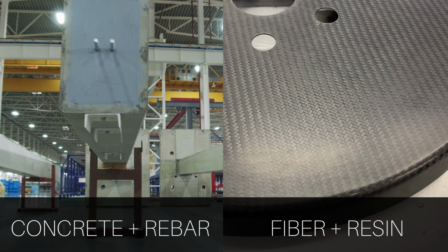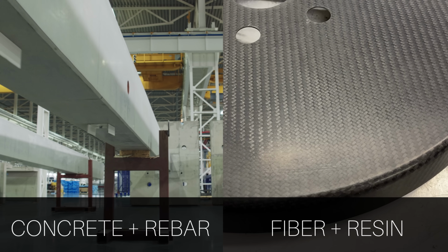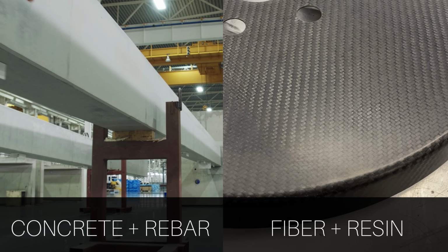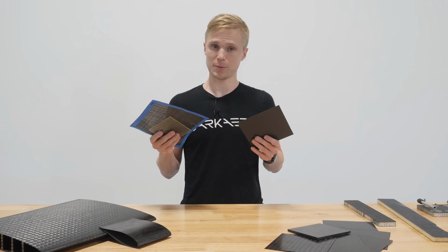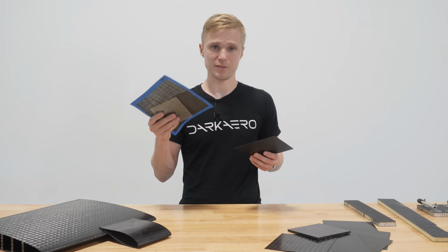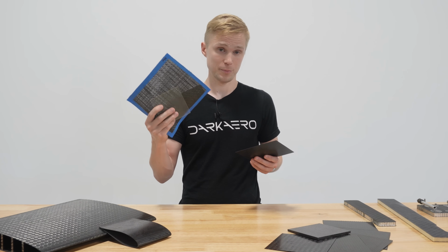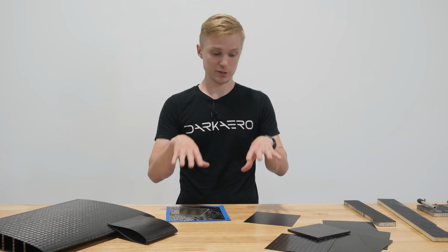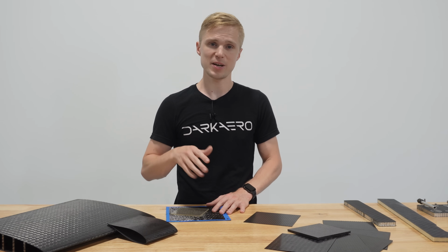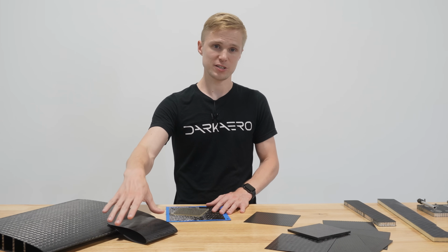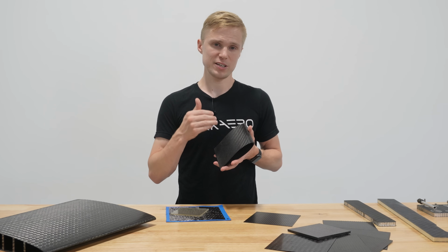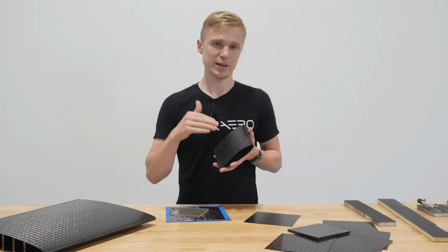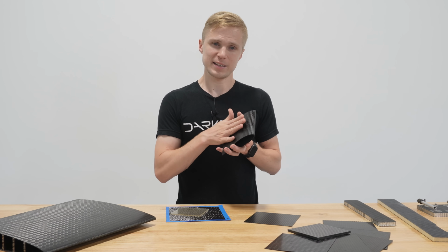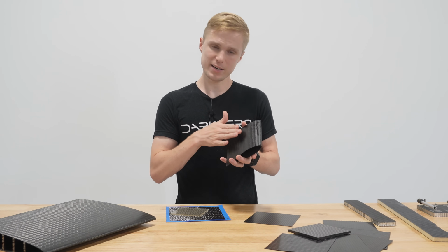When both are combined, they create a new material that has properties which are a blend of the concrete and rebar properties. In a similar sense, carbon fiber composites have properties that are a blend of the fiber and resin that they are made up from. The cool thing about fiber-reinforced composite materials like carbon fiber is that they can be customized and optimized for a given application. The fibers in the material can be arranged so that they line up with the loads that will be applied to a structure. This allows more strength and stiffness to be added where it is needed.